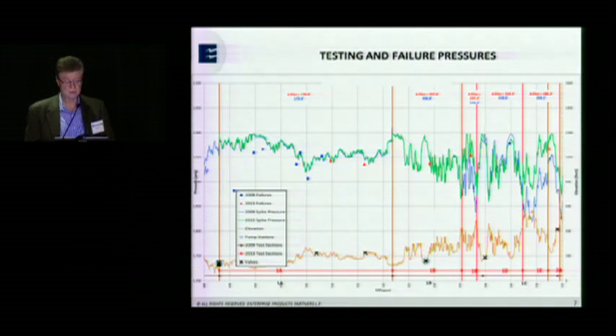And then in 2013, you can see the red triangles. Basically, in all cases except one, they are matching the hydrostatic test pressure. There was one that failed at 13 PSI lower. That one did actually get to the higher pressure, then another section of pipe failed, and when we repressurized it, it did fail at a lower pressure. So we saw a pressure reversal on that.